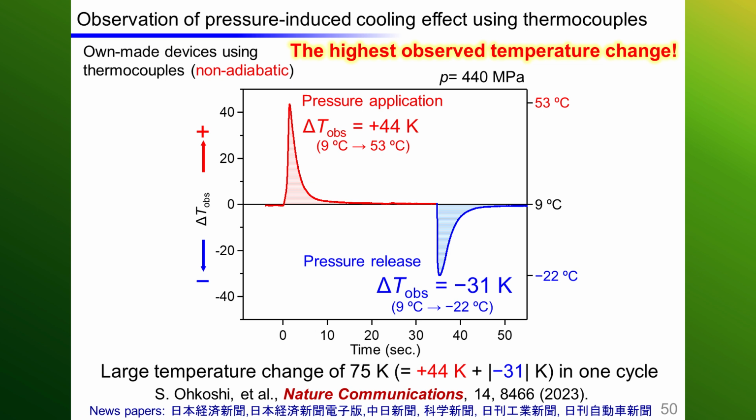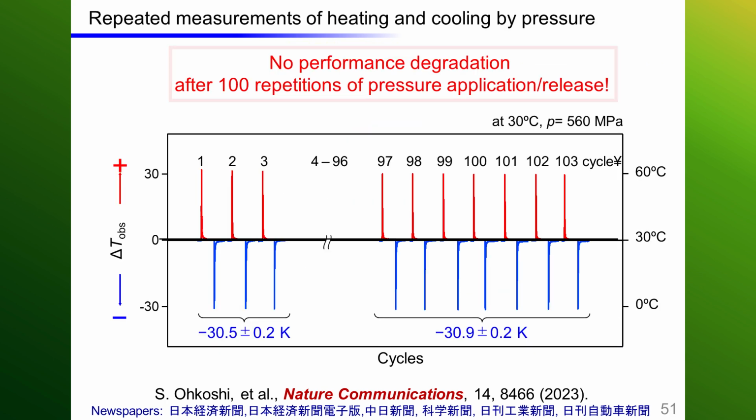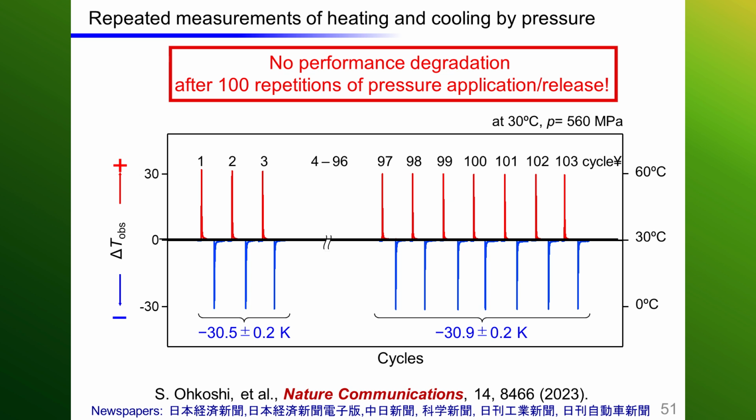We then examined the performance of the device when measured repeatedly, and it amazingly maintained the same performance even after 100 repetitions, with no degradation in performance. I was also surprised at the reproducibility of this material.